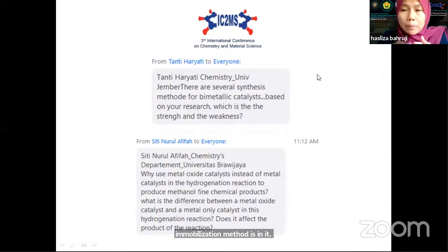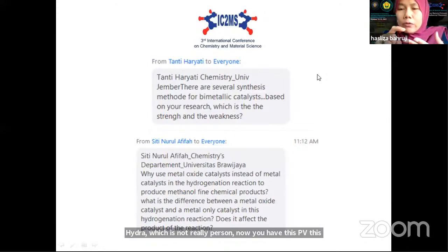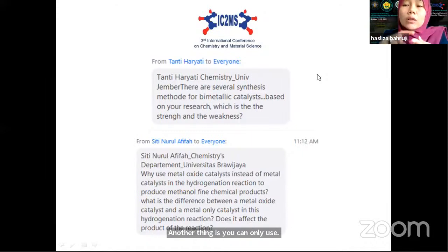You require a reducing agent, sodium borohydride, which is not really pleasant. And then you have PVA as a stabilizer, which, if there is too much, can start to poison the surface of the palladium. Another thing is you can only produce palladium zinc alloy on a zinc oxide support.